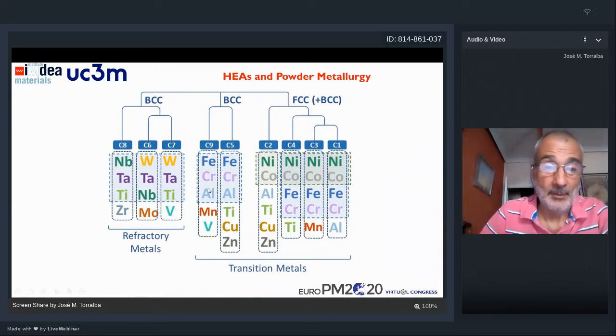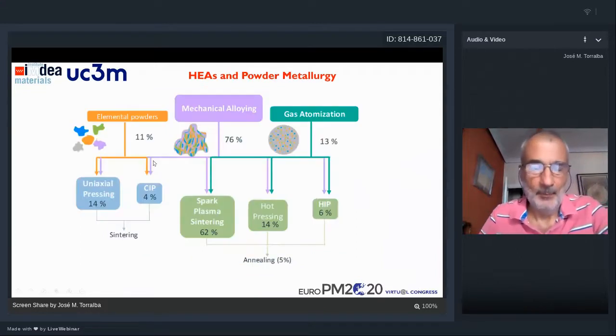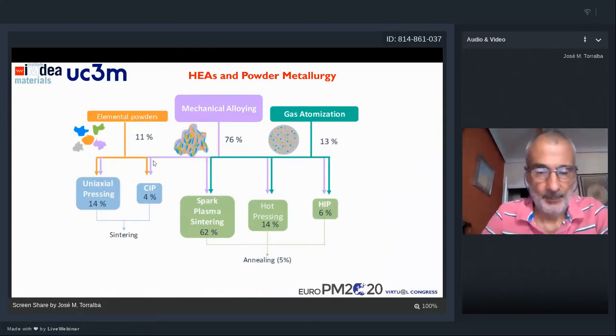The addition of aluminum and other elements can produce the movement from the FCC phase to the BCC phase, and in the case of refractory metals, most of them present the BCC phase, a single phase. How can we produce high entropy alloys by powder metallurgy? If we analyze the literature, 76% of the papers report mechanical alloying as the main way to produce the powder. Then we have a small amount, 13%, of gas atomization, and some other papers use a mix of powders to develop the high entropy alloy.